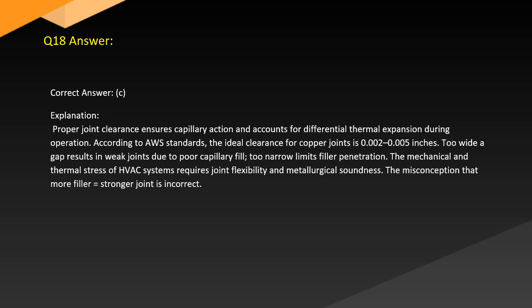Answer. Correct answer: C. Explanation. Proper joint clearance ensures capillary action and accounts for differential thermal expansion during operation. According to AWS standards, the ideal clearance for copper joints is 0.002 to 0.005 inches. Too wide a gap results in weak joints due to poor capillary fill. Too narrow limits filler penetration.